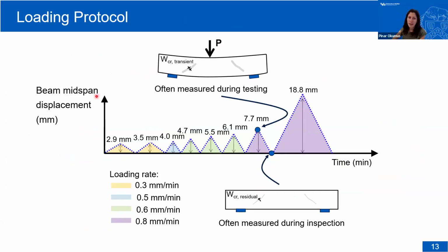Our loading protocol, like I said, was cyclic. This is the beam displacement versus time, our loading protocol. So we load, unload, load, unload, load, unload. One very important thing we can get from this type of testing is that we collect data when we load the beam, and that's your transient crack width. We measure the transient crack width when there's a load on the beam, because this is what all the literature is reporting, because they're running monotonically increasing loading tests. So all the crack data that we have in the literature is really for transient cracking. But nobody reports residual crack width. Residual is after you remove the load, what's that remaining crack? And it's important because that is what's measured during inspection. And again, there's no data that links the two crack widths together. So we wanted to get a sense of that.